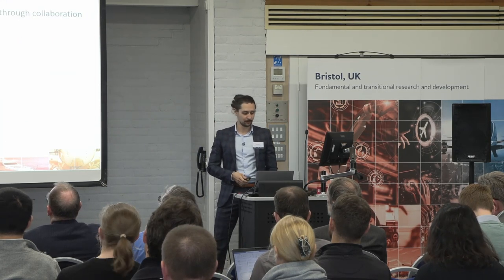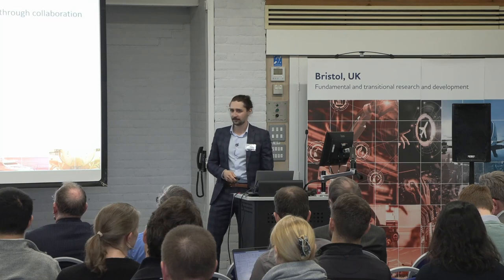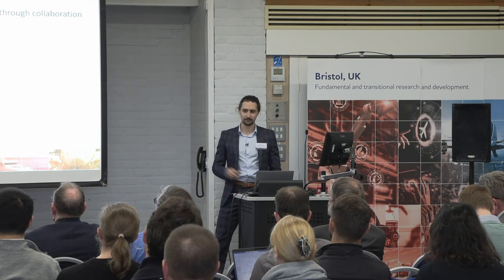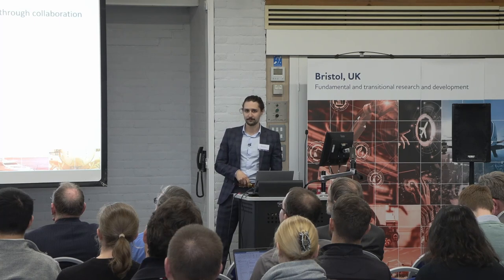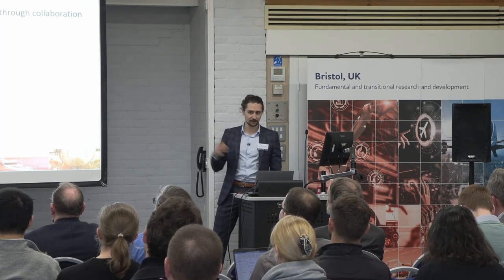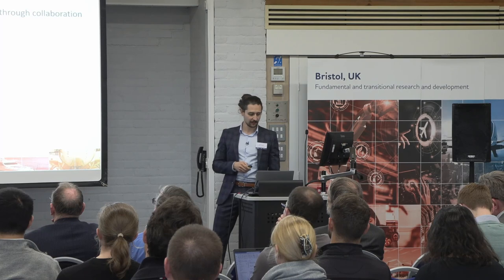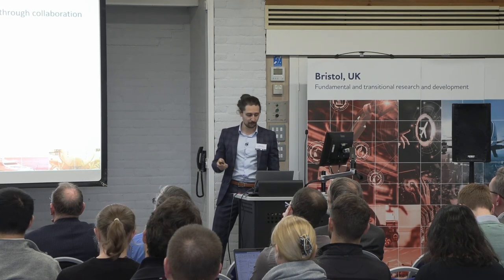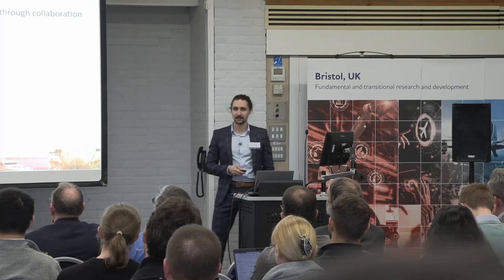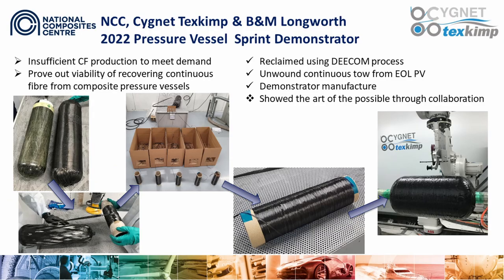About a year and a half ago, we did a little demonstration piece of work to showcase this potential solution. We started with an end-of-life pressure vessel. We put it through a thermal recycling process to remove the polymer and expose the carbon fiber wrap. We then manually unwound that at NCC and re-spooled it back onto bobbins. Then we collaborated with Cygnet Texkimp to demonstrate wet filament winding with these recycled tows back onto a Type 4 pressure vessel liner, a sort of tank-to-tank demonstration, really showing what's possible.